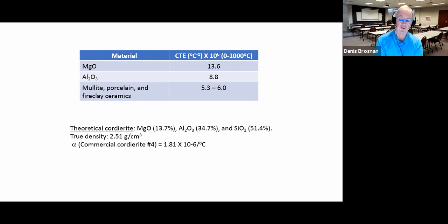And the reason that's interesting is that the thermal shock resistance is inversely proportional to the thermal expansion coefficient. So if the thermal expansion coefficient is low, the thermal shock resistance is very high. When you heat and cool the ceramic, there's not as much dimensional change, and that's what causes stress in thermal shock events. So cordierite ceramics are used where thermal shock resistance is really needed.